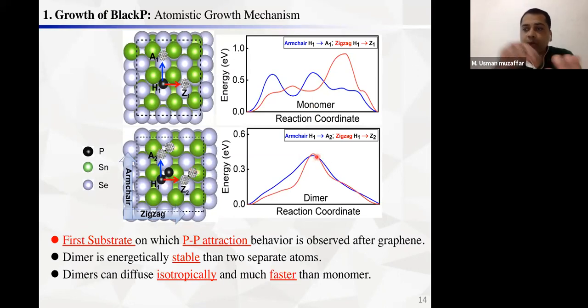So it means that if we give more and more atoms, they will form dimers and move faster and form a black phosphorene. So this is the first substrate, the tin selenide substrate, with PP attraction. PP attraction means the two phosphorus atoms attract each other and then they form dimers. This behavior is also observed in graphene, in the case of the tin selenide substrate. So this is the first case, the black phosphorene case.